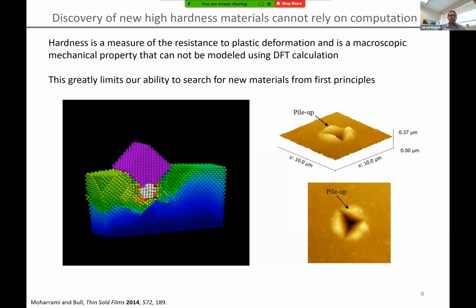And then there's other issues we also have to consider, and that's the fact that when we're indenting a surface, it's not like we have a shovel and we're just scooping the atoms away off of the surface. If you look at these AFM images, what you can see from the indentation is that the atoms have to go somewhere as you push on the surface.